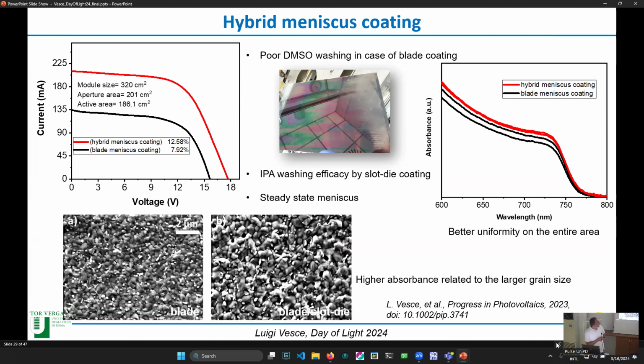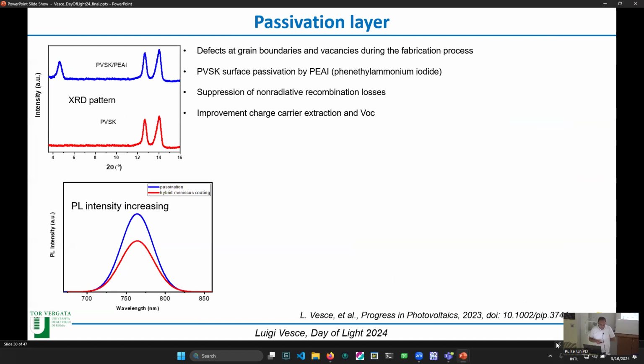For example, the red is related to the hybrid meniscus coating. I mean, hybrid is blade plus slot die, and blade is the black one. So you have some difference because of this behavior. And also the higher absorbance in the hybrid meniscus coating is related to the bigger grain sizes that you have in the same image.